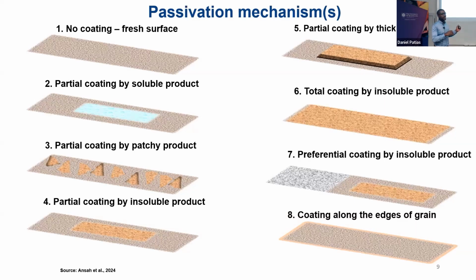In this case, it affects how much copper you can get into solution. If you start from a fresh surface, there's more copper, and you could be forming things which are soluble, if you're lucky. If it's soluble, it means it comes back and then you could get your copper. But if it's thick and dense, then you don't actually get much copper in solution. If it's porous, we think you could still get your fluid permeating through the pores and contacting the primary copper surface.